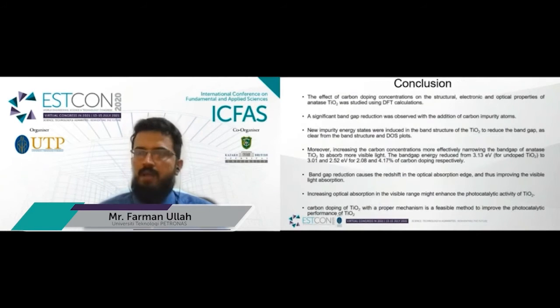Conclusion. In this work, the effect of carbon doping concentration on the structural, electronic, and optical properties of anatase TiO2 was studied using density functional theory calculation. The main finding of this research work is that a significant band gap reduction was observed for the addition of carbon impurity atoms to the TiO2. New impurity energy states were introduced in the band structure of TiO2, as confirmed by density of states plots. Moreover, increasing the carbon concentration more effectively narrows the band gap of anatase TiO2.